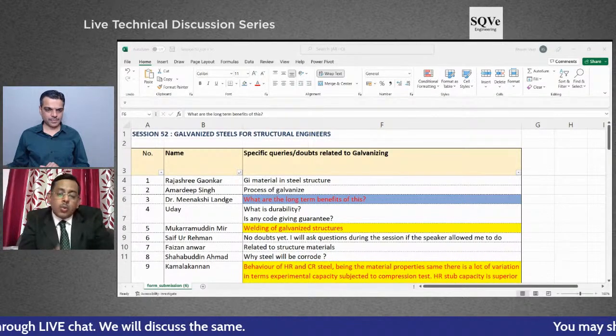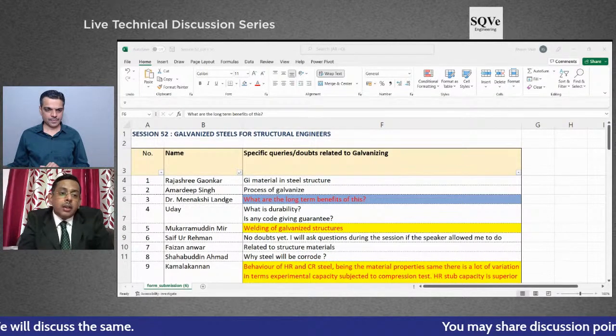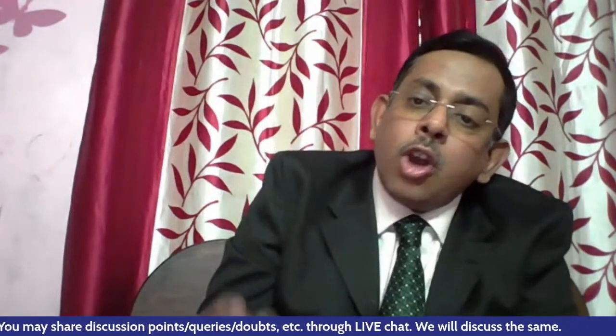Galvanizing means you are having a good protection. Weathering, that means atmosphere, when it wants to react with the steel surface, it has to come across a barrier of 200, 300 microns of galvanized layer. Then it can touch steel.